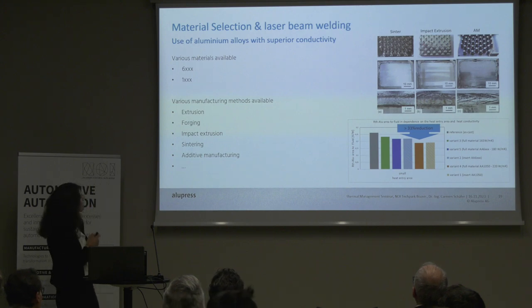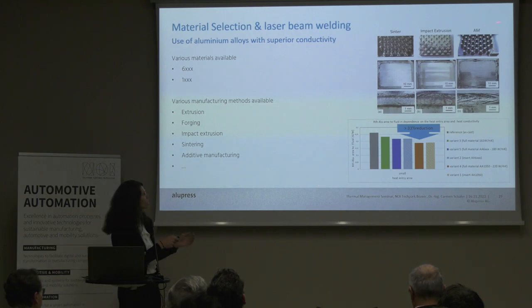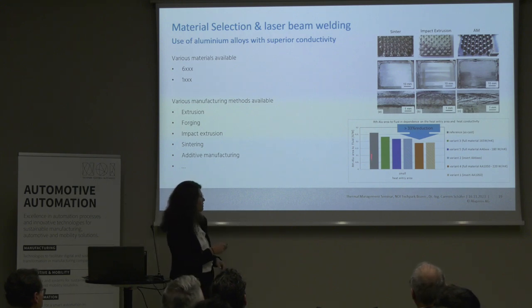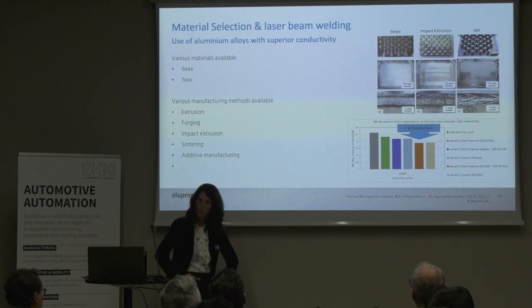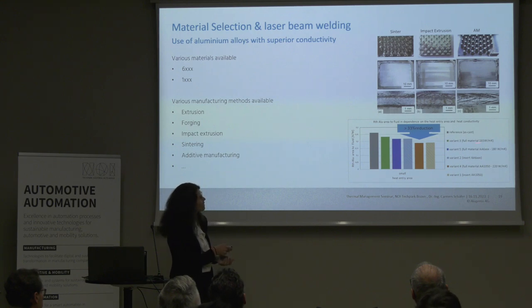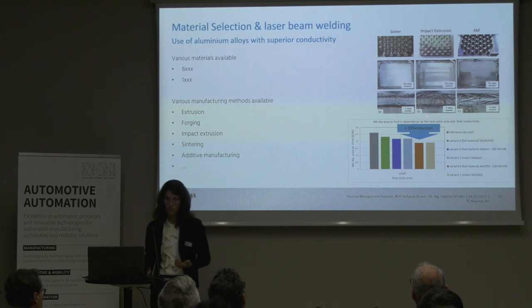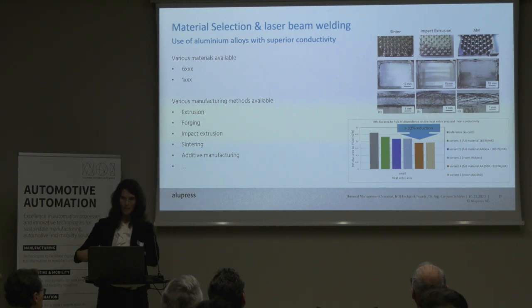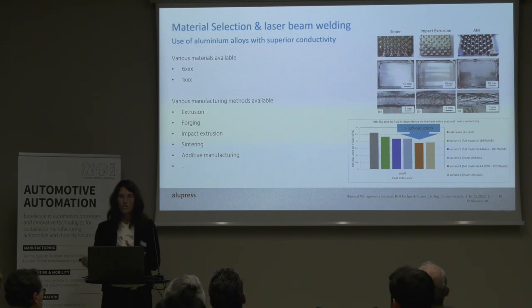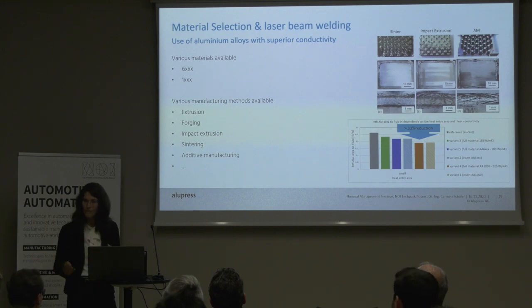So I can combine good alloys, but I can also take various manufacturing processes, such as sintering, impact extrusion, or additive manufacturing, and weld it in the die cast housing. And what I get from this is, for example, the thermal resistance that I mentioned at the beginning, which we want to push down. This is not that good in a die cast housing. If I go with various conductivities down to the orange bars, I already have a reduction of 33%. So if you add up all the reductions that I showed, there is quite some potential still in the die cast housings without changing to a completely different system.